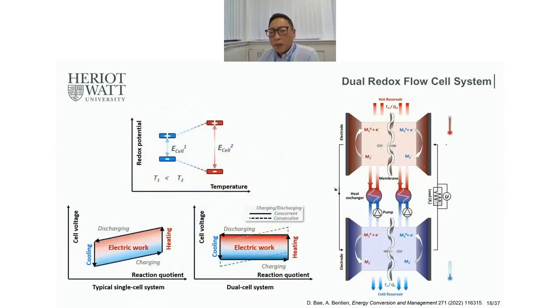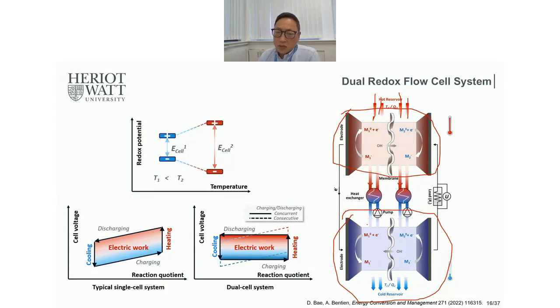It is because the hot cell absorbs the heat from the outer source and operates the redox reaction, and the other cell on the cold side works for discharging the electrolyte which has been charged at the high temperature. So unlike this typical single cell system, in terms of the cell voltage and state of charge behavior, if we use this type of system, then we can keep the cell voltage always the same, if both charging and discharging reaction rates are the same.